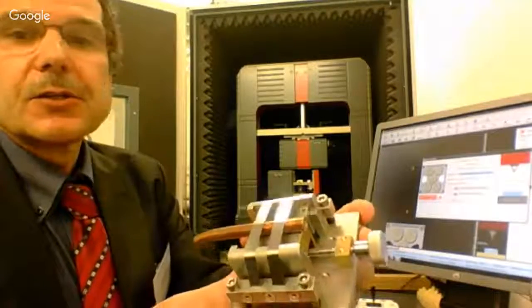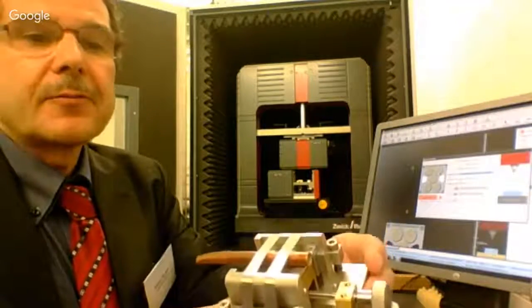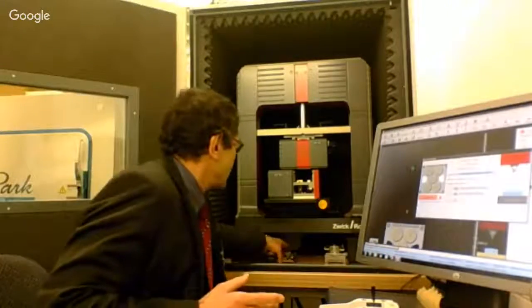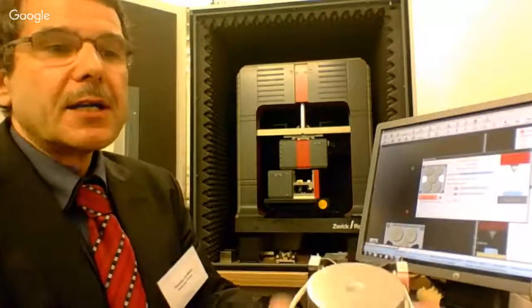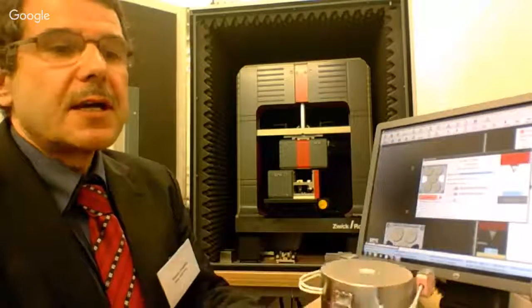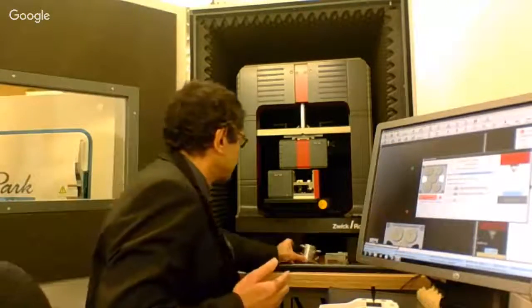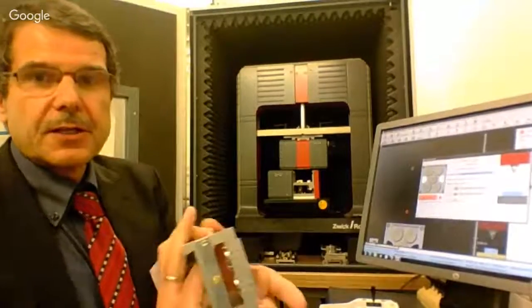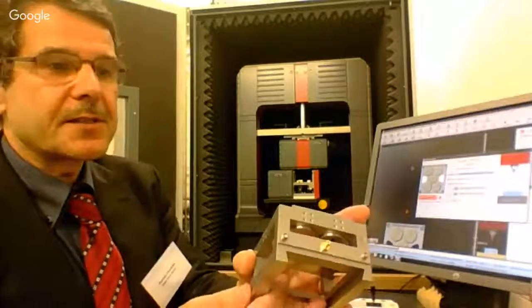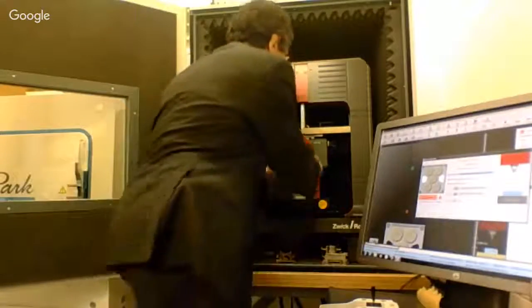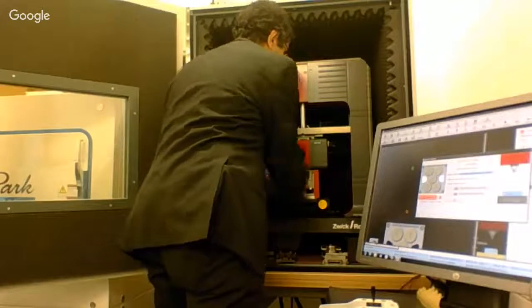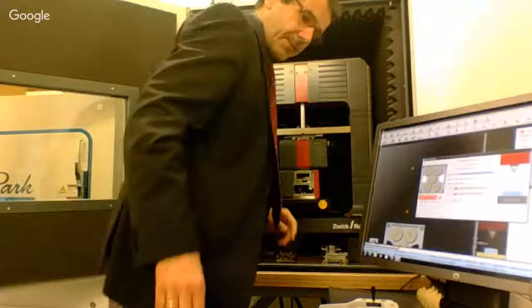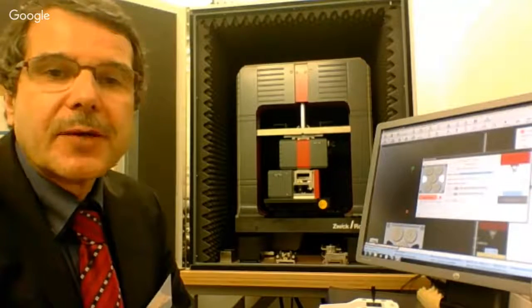There's another sample holder where you can clamp larger samples, so tubes or other things, and fix them without gluing the samples. And we have also a heater, which is installed instead of the sample holder, with an extended shaft going inwards with a tip. You see here the contact for the contact resistance measurement. Now I install the holder again. So it's a stop, and the reproducibility of the installation is quite high, so plus minus 10 micron is normally possible.